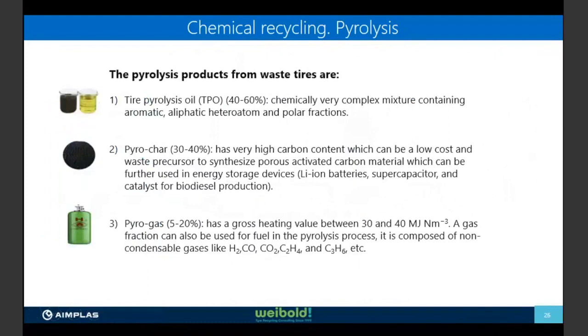Then the three pyrolysis products that we obtain from waste tires are the pyrolysis oil, pyrochar, and pyrogas. The pyrolysis oil, which we are going to call TPO, you achieve around 40 to 60%. It's a chemically very complex mixture. Mainly, it contains aromatic, aliphatic, heteroatom, and polar fractions.